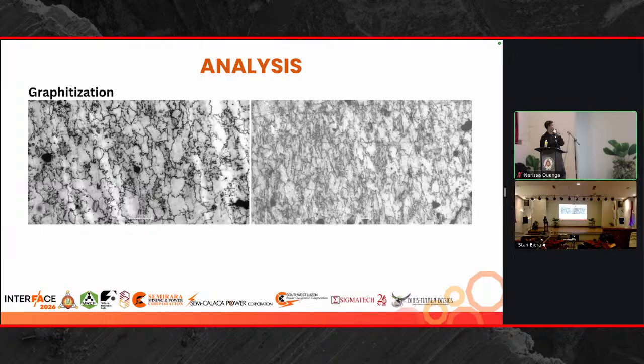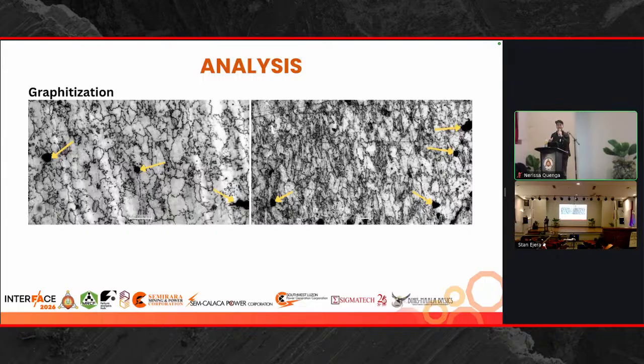As we can see here, these graphite nodules are found randomly within the microstructure at the base metal and at the heat-affected zone part. This can act as stress concentrators in the microstructure, and that's why we are also concerned with observing these microstructures in our samples.